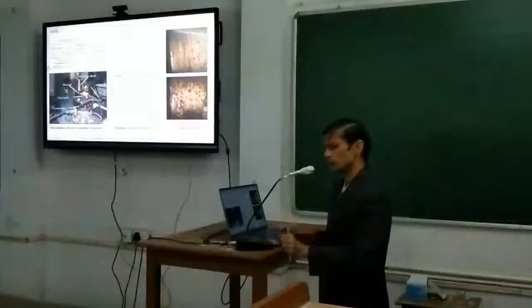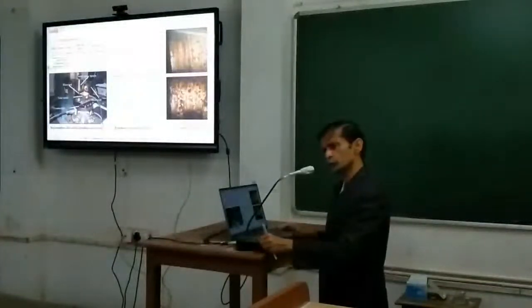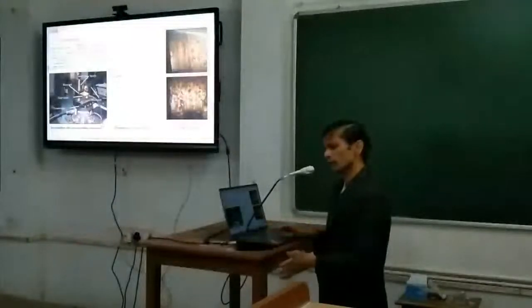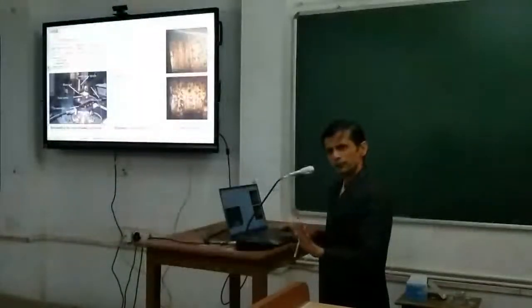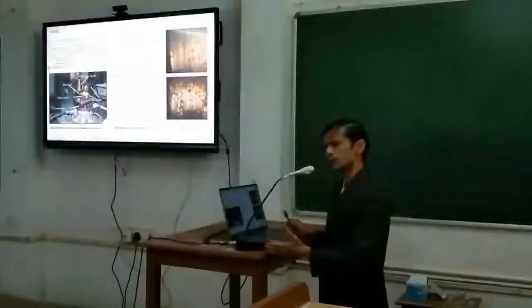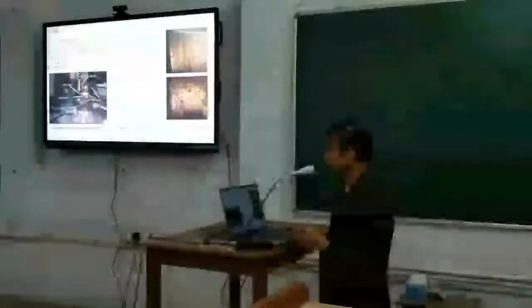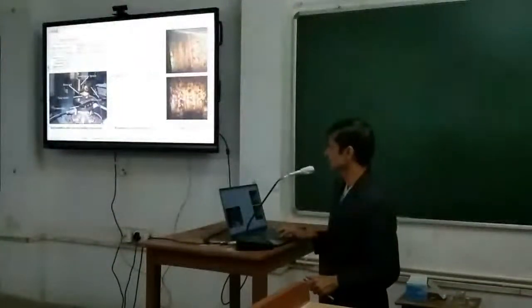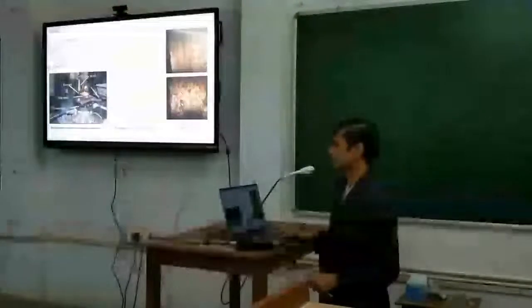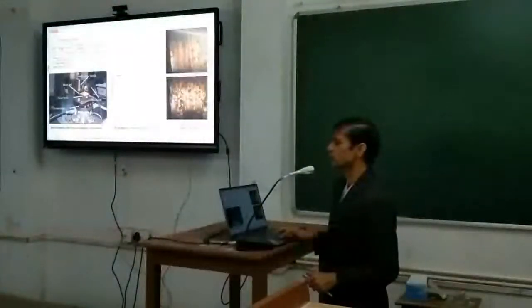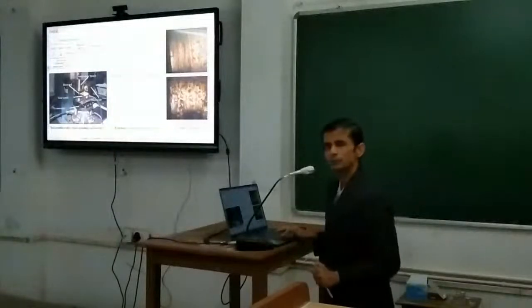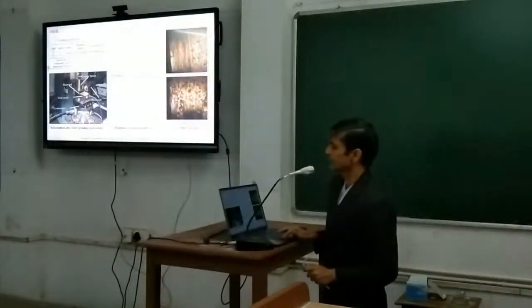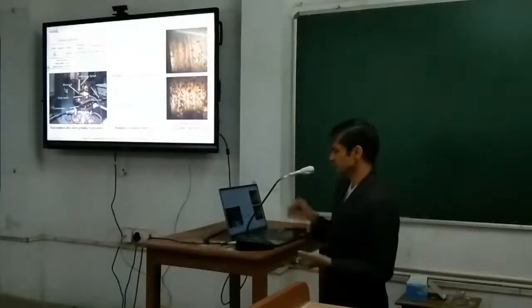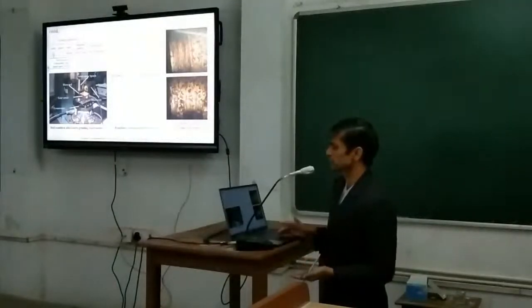So sometimes you just need the microscopic contours and may not be that bothered about the form and all those things. It may happen, okay? But when your precision requirement is very, very high, this tool is not suitable, because you can see after some amount of grinding, the grits are getting dislodged, right? And again, you can see the Vw is in micrometers per second, so 300 micrometers per second, that is 0.3 millimeter per second, very low, and the velocity is 4 meters per second, which is also not very high. So it's quite low. So this is how things are.